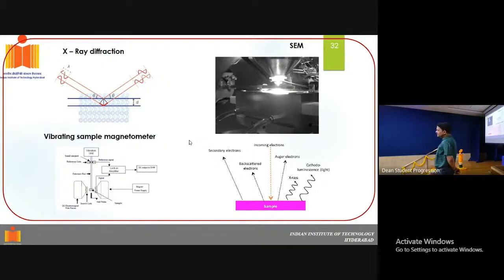The backscattered electrons, from the nucleus of the atom, will give information about different phases. Suppose we have an A phase and a B phase, so there will be color contrast from the backscattered electrons. On top of that, the X-rays will give information about the composition of the material. That's why it's called energy dispersive X-ray spectroscopy. It is not because of the electrons that we are able to get the composition of the material. It is because of the X-rays.